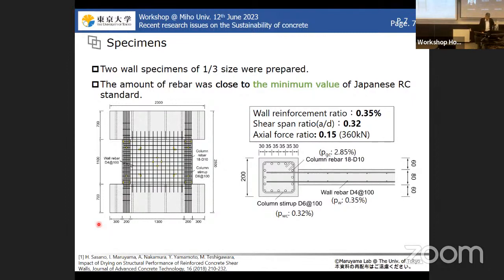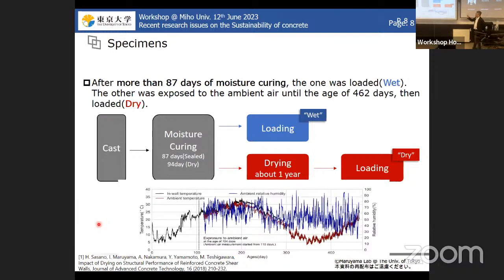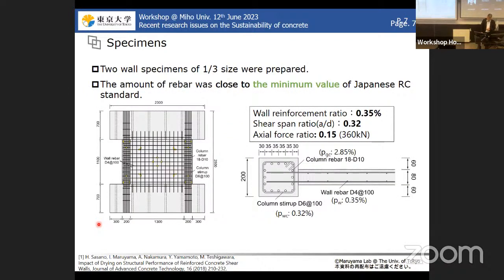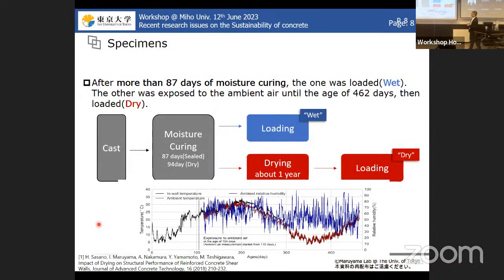I cured the specimen for a long period because additional hydration is not desired for this experiment. So I cured the specimens for 90 days, and then I loaded one specimen. The other specimen was exposed to a drying environment for 1 year, because the thickness of the wall is about 8 centimeters, so it is easy to dry out. After reaching almost equilibrium, I loaded this shear wall.